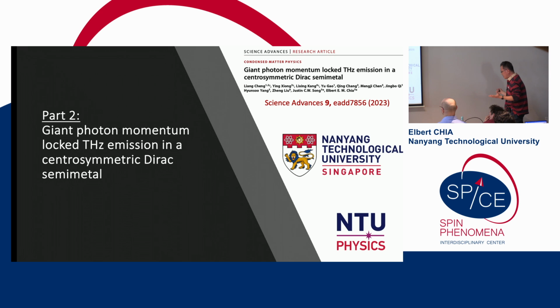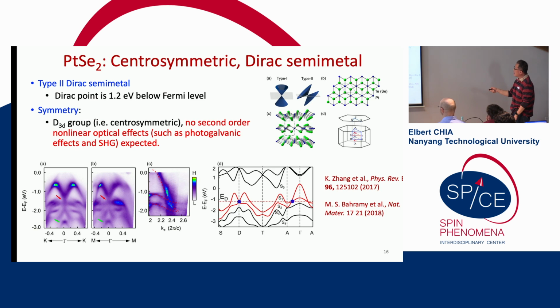For part two, instead of a semiconductor, we went to a semi-metal, and it is actually a Dirac semi-metal, which is platinum diselenide, which is centrosymmetric, where the Dirac point is about 1.2 eV below the Fermi level. And because this is a centrosymmetric semi-metal material, we should not expect any second-order nonlinear optical effects. But we still went ahead to do this experiment.